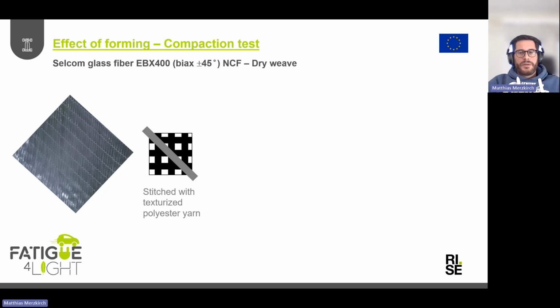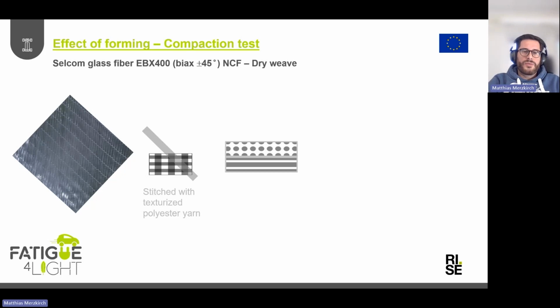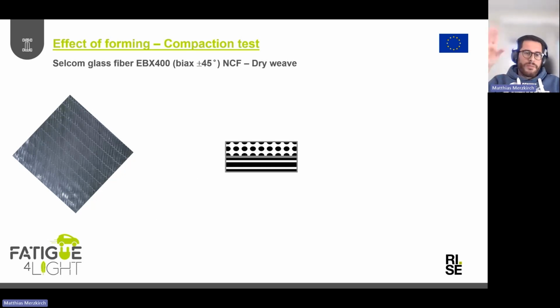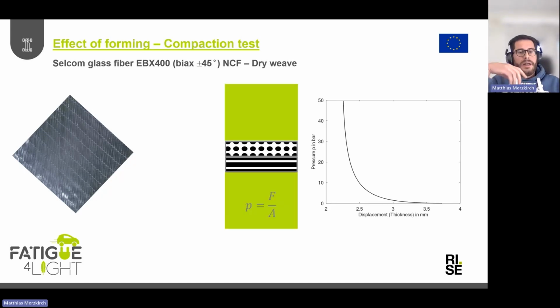To understand how we should do the layup, I'm not going too much into the design of this lower control arm, but it's more to understand what kind of volume fractions we can achieve. There's a so-called compaction test. We put up a certain layup, a biaxial layup with fibers pointing in horizontal direction. We use 10 biaxial layers, so overall 20 single layers. And in that case, we just compress them, pretty easy. When you increase the pressure, you can very well imagine the thickness changes. So you get from a compressive force towards a pressure and the change in thickness.